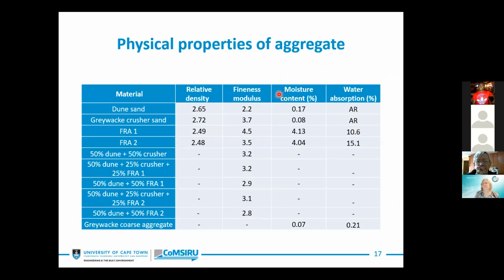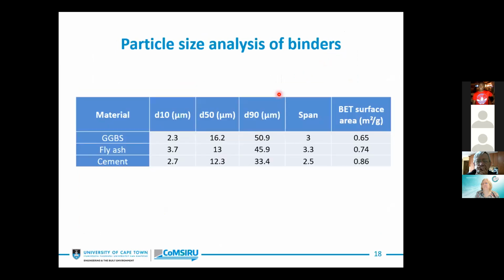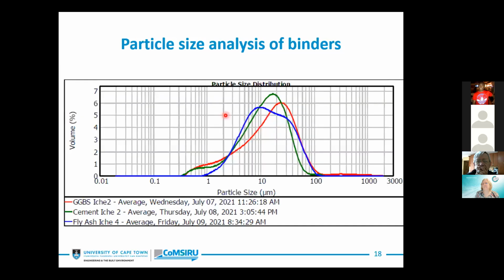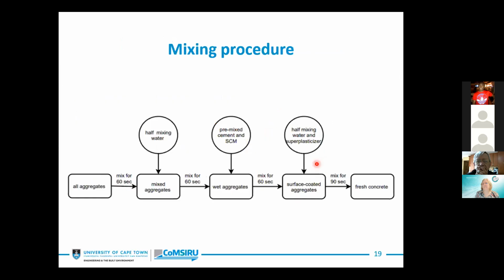Here are some properties of aggregates measured in the lab: fineness modulus, moisture content, and all of that. Some of these were used, of course, for the mix design. And for our binders, we did some basic characterization like particle size analysis, and we can see that all of our binders do not exceed 51 microns for the D90 sizes. And of course, our BET surface area is given there.